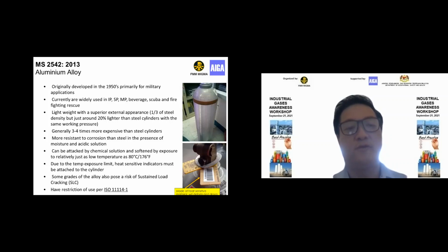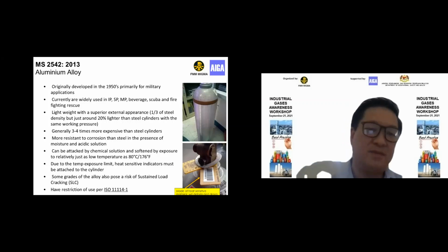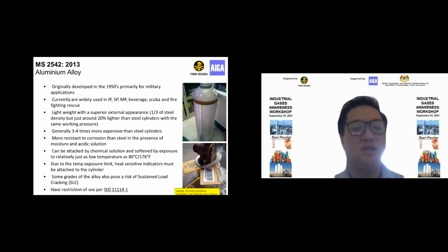It is good for corrosion that affects steel, but as said, moisture and acidic solutions are an issue. Heat is also a problem. Therefore, plastic test rings need to be used to detect if the cylinder has been subjected to heat. The normal temperature we would control it at is around 80 degrees C. So when we put it in the outdoor environment, we would normally put it in the shade. In the sun is okay because the heat of the sun on the cylinder will normally bring it up to about 60 odd degrees C at the most.